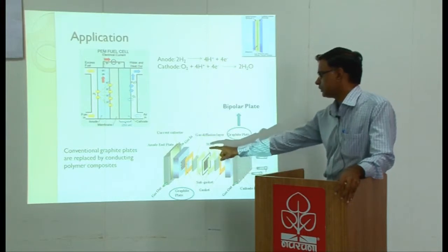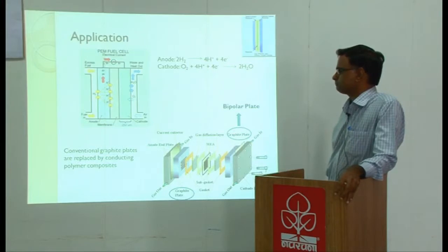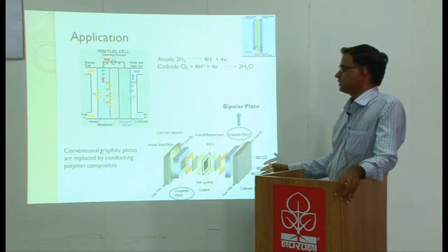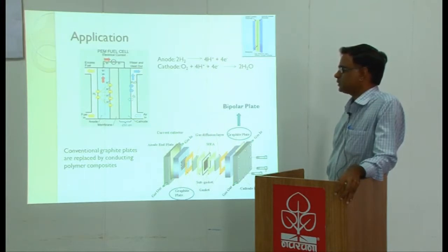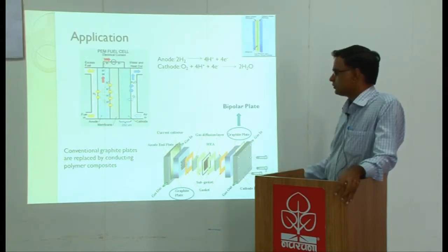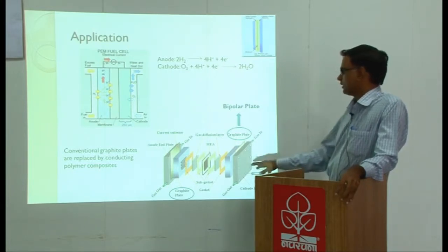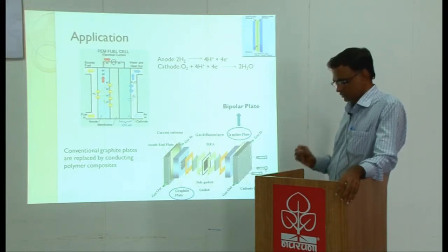So, now the question is that making this flow field onto graphite is a bit difficult, because graphite is brittle. So, it adds to the cost of the entire fuel cell. Of course, one can think of metals. Metals by default have more density, and also in this operating condition PEM fuel cell operates at around 80 degrees C. There is a possibility of getting corroded, because we will be using Nafion membrane predominantly in proton exchange membrane fuel cells. Not only that, recently sulfuric acid doped polybenzimidazole membranes are being used. So, depending upon the nature of the membrane, there could be a possibility of corrosion when we use metallic bipolar plates.